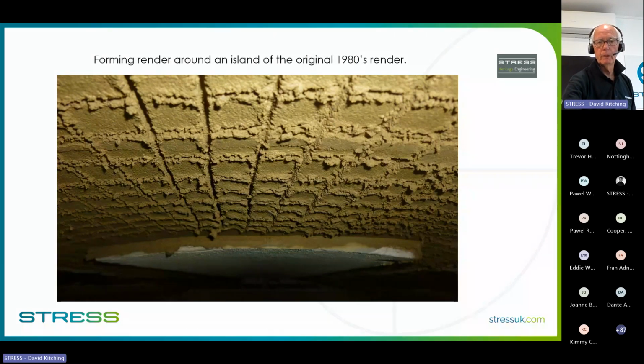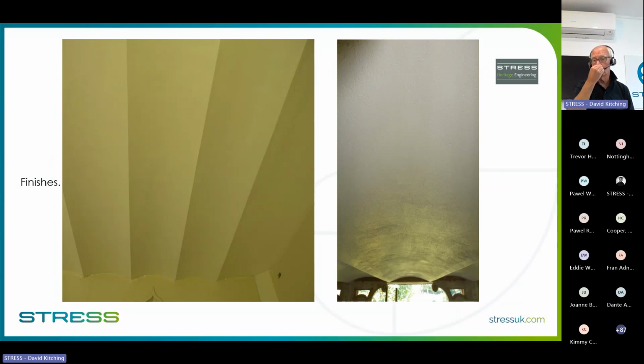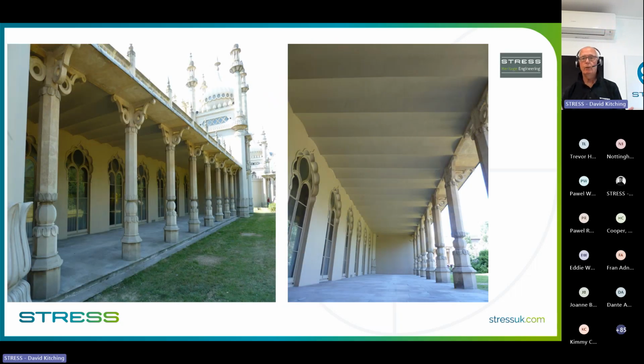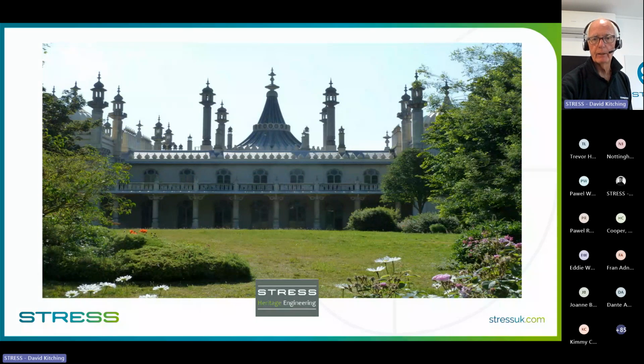So there's a scratch coat going up, and there's the completed items. That's all done by hand. John was the master plasterer, you saw him earlier on, and you end up with basically something that you can't tell that carbon fibre has been used. So there you are. So you will now know if you go to Brighton Pavilion that in fact that Adelaide balcony is strengthened with carbon fibre sheet. That now has a factor of safety in excess of 2. So if you go to a wedding up there, you can quite happily jump around and dance on that balcony. Fully completed, very happy client.